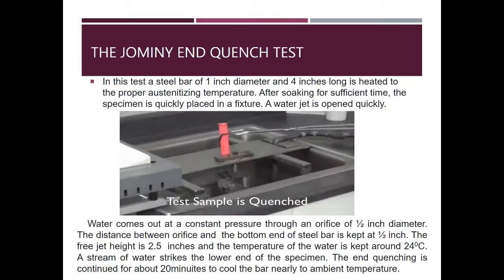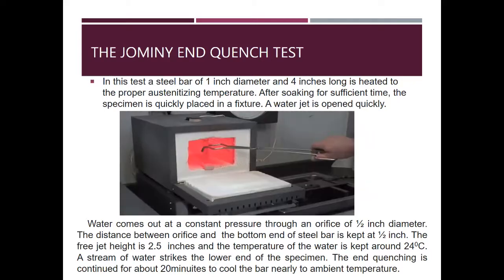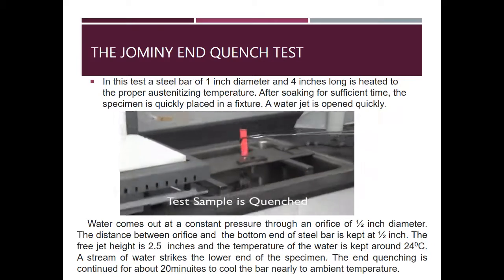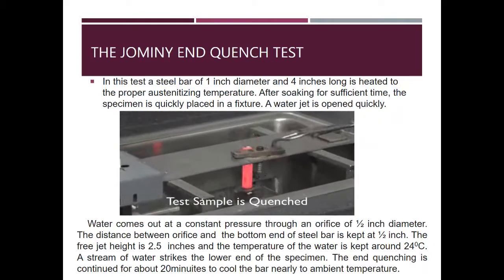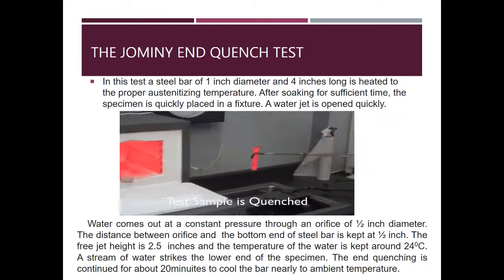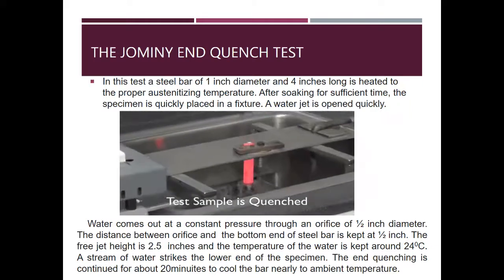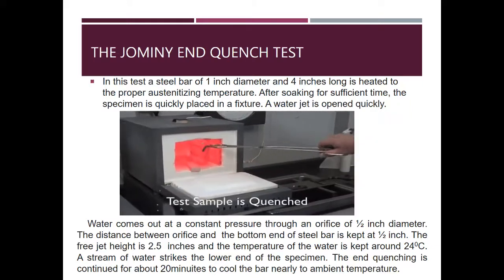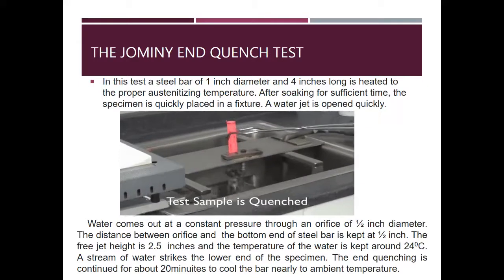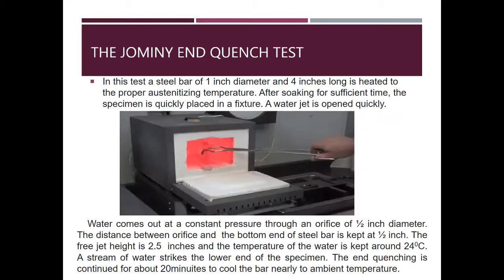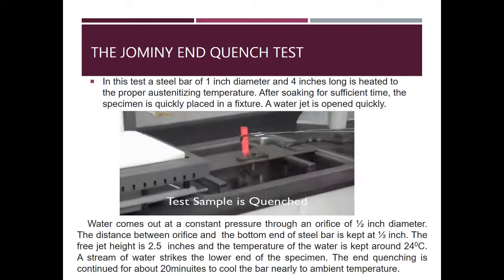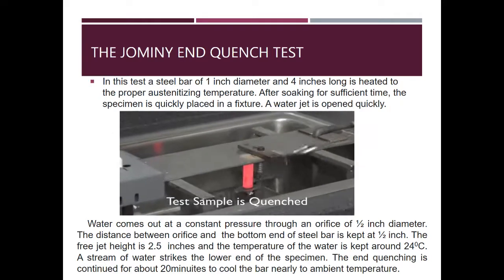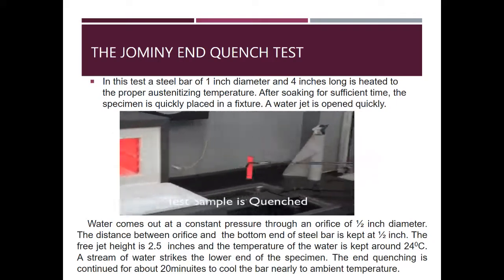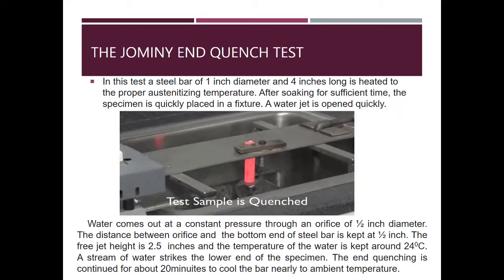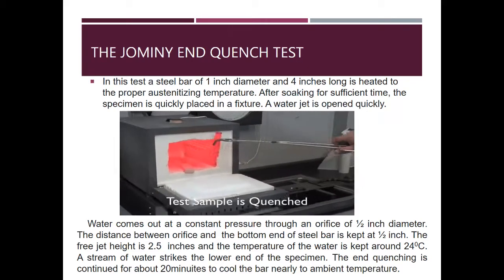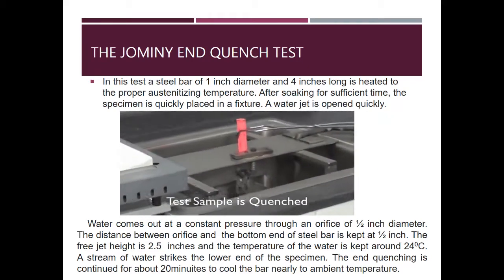Water comes out at a constant pressure through an orifice of ½ inch diameter. The distance between the orifice and the bottom end of the steel bar is kept at ½ inch. The free jet height is 2.5 inches and the temperature of the water is kept around 24 degrees centigrade. A stream of water strikes the lower end of the specimen. The end quenching is continued for about 20 minutes to cool the bar nearly to the ambient temperature.